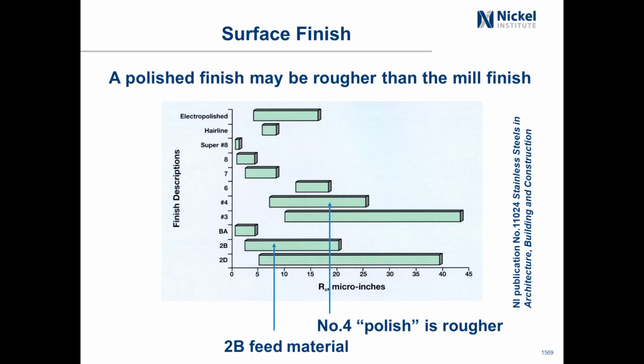But you produce number 4 by polishing 2B, which is a cold rolled finish. And the range for cold rolled finishes is from here to here. But when you polish number 4, in fact, you can make it rougher than what it was as a cold rolled 2B. But even still, the maximum we're showing here is about 25 microinches, which is less than the 32 that's required by EHEDG and 3A.